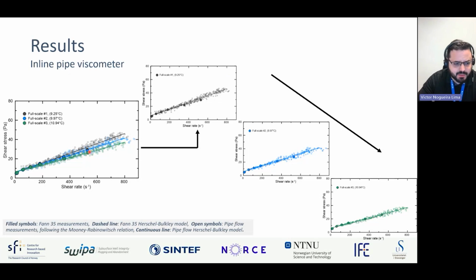Then when you go to the filled symbols, the green, blue, and black-gray ones, those represent the measurements that we got from the FANN 35, the rotary viscometer measurements. You can still see a very good agreement between the two instruments. And finally, the dashed line is the Herschel-Bulkley fit to the FANN 35 measurements. So in this first graph, we have the 3 sequences that we did in the pipe viscometer all together. Then we separated the 3 measurements into single curves, as you can see on the right-hand side. And here it's clearer that we still have a very nice agreement between both instruments, and also between the rheological models and the data that we got.